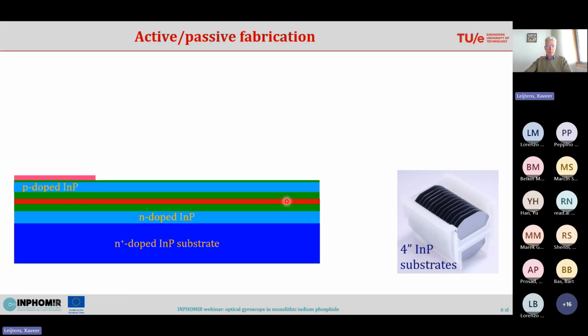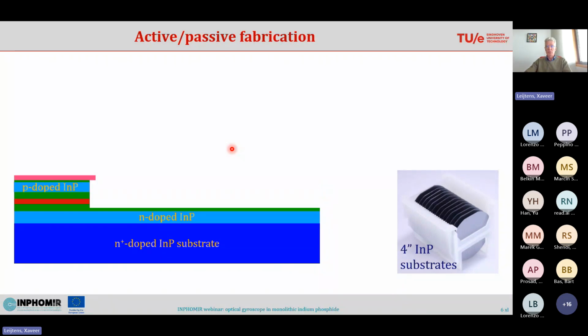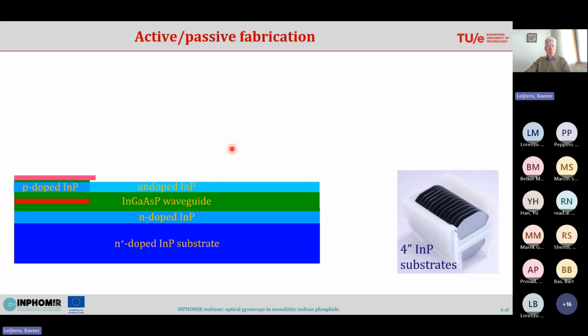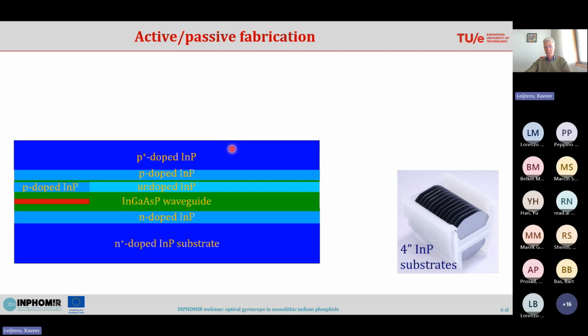And then we stop, and we mask the parts which are to become the amplifier and the detector. These share the same cross-section. Then we etch away the active part in most of the wafer and keep active parts only where we need the amplifiers and detectors. And then we regrow with a passive, transparent material, indium gallium arsenide phosphide. We regrow the core of the waveguide, which is the guiding layer. We regrow undoped indium phosphide, and we remove the mask and then grow a common cladding layer on top of it. And then finally, there's the contact layer as well.